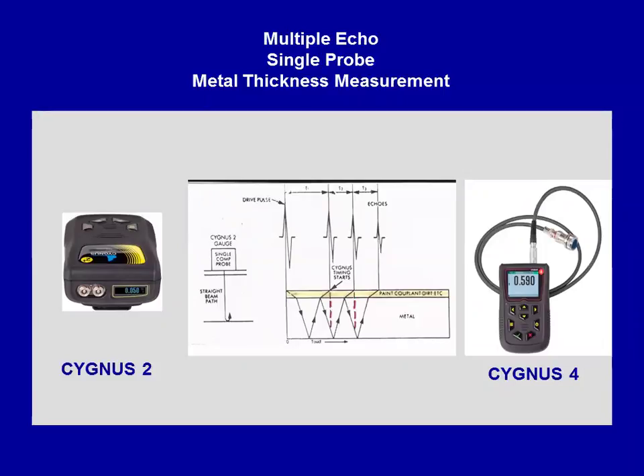The most obvious advantage of this technique is you do not have to take the coatings off, as long as they're bonded, not flaking or peeling. If they're peeling, peel them off. They have to be bonded to the surface. That's the most obvious advantage, but it's about accuracy. You get a true, accurate, verified thickness measurement.